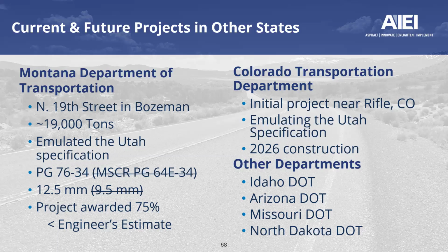There was an issue, however, with the binder. It did have a rotational viscosity that exceeded the typical Utah spec. They did drop the Utah spec in, but they did not hold that binder to it in terms of rotational viscosity. And the upshot was that the contractor had some issues with their pumps getting hit with some high amperage, and therefore they had to essentially choke their plant back to keep the amperage on the pumps at an acceptable level.